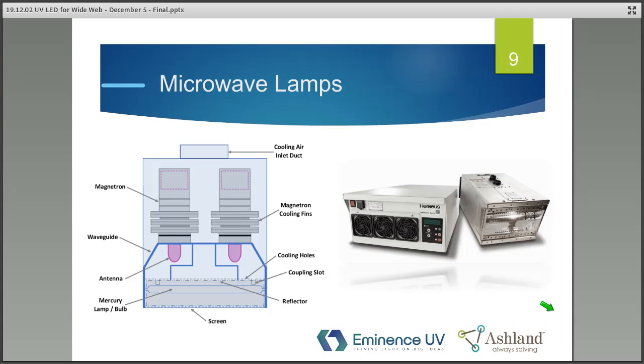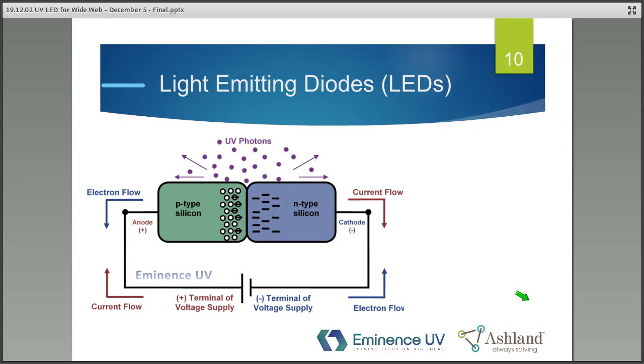A microwave lamp is also used in the industry. Many of your converting applications will use microwave lamps. They come in 6 and 10-inch lengths, and you pretty much mount them end to end to get whatever longer length you might need. The mercury bulb is this illustration, this line drawing here at the bottom. It's a sealed quartz tube just like the arc lamp, but there's no wires on the end. Effectively, we're generating microwave energy from these two magnetrons, and as that microwave energy hits the mercury inside this quartz tube, it vaporizes it into a plasma gas and emits UV light. So there's just two different ways of generating ultraviolet energy. Both of them rely on mercury inside a quartz tube, which is very different from LED technology, which is what you see on this screen.